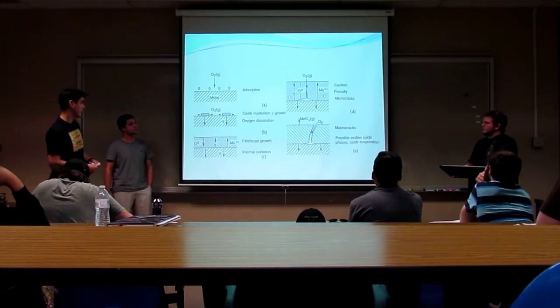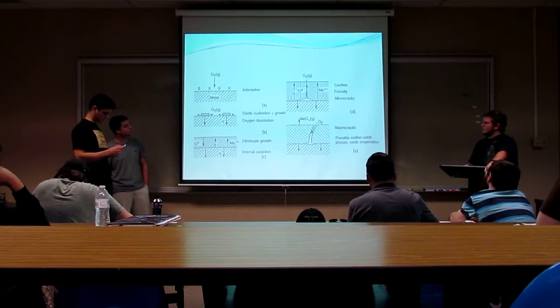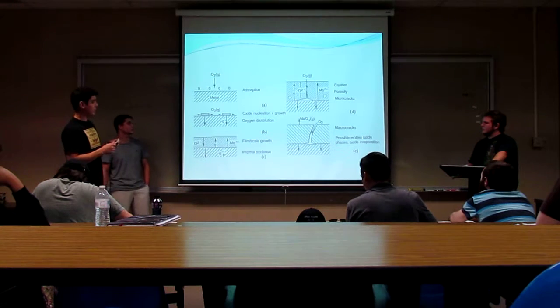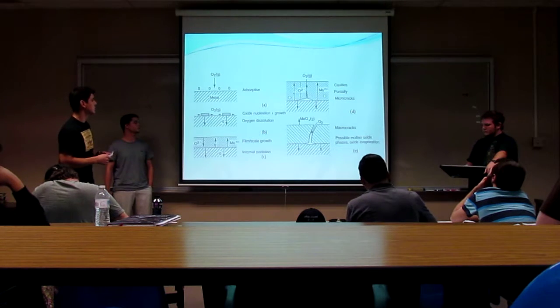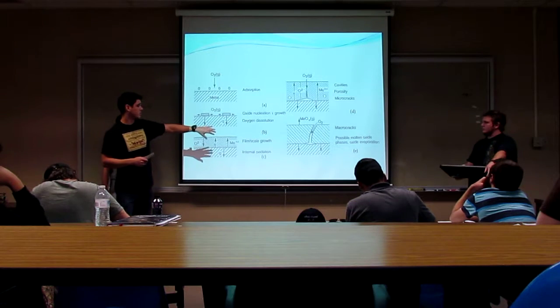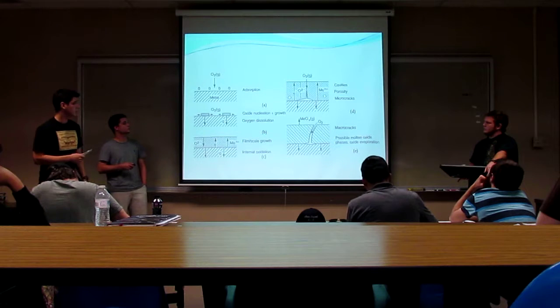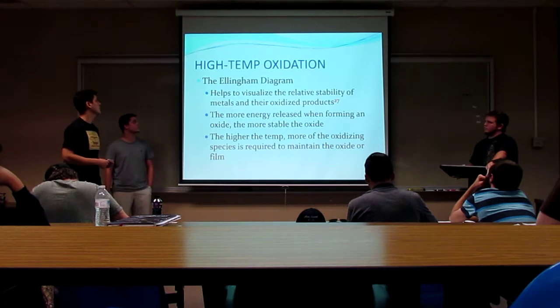If it's a carbon steel, you're going to have micro cracks because the carbon diffuses with the scale in the base metal and reacts with iron oxide to evolve CO2 gas. That CO2 gas is going to build up, and then it's going to cause cracks in your oxidation layer, in your scale buildup.